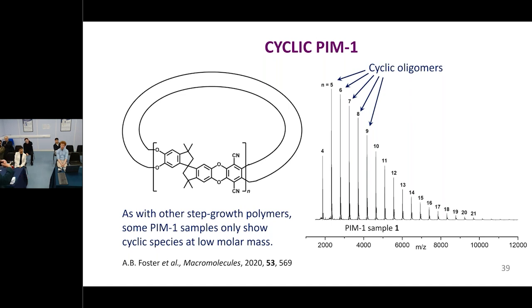That's because if you're doing this sort of polymerization, if the ends join up and you get a cyclic, nothing more is going to happen to it. If it's a linear oligomer, it can go on to react. So if you push the reaction enough, what's left at low molecular weight tends to be the cyclics. So most step polymers, if you do mass spec, all you see is cyclics. It doesn't mean that it's cyclic over the whole distribution.